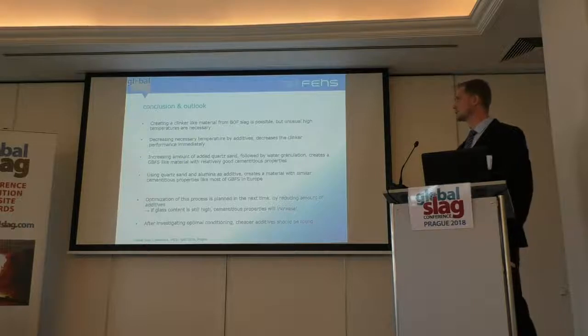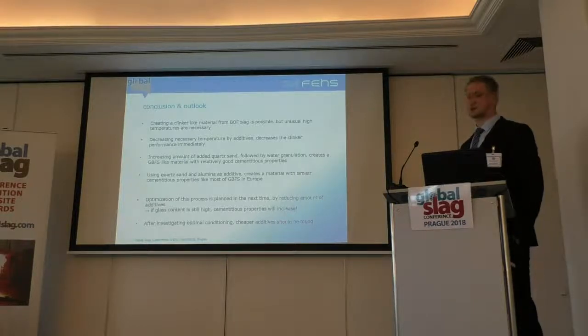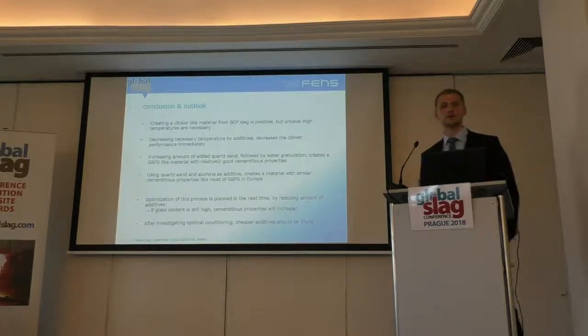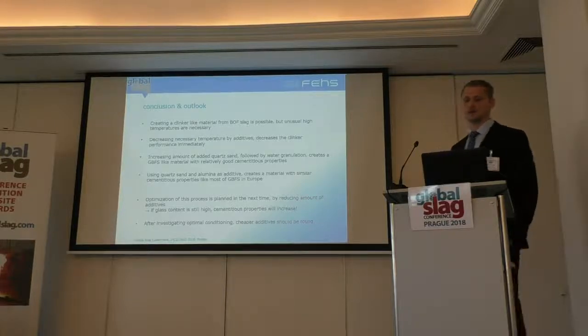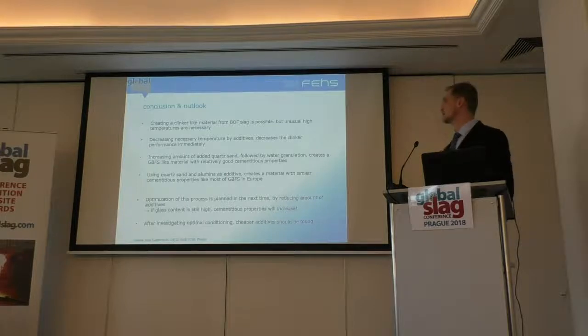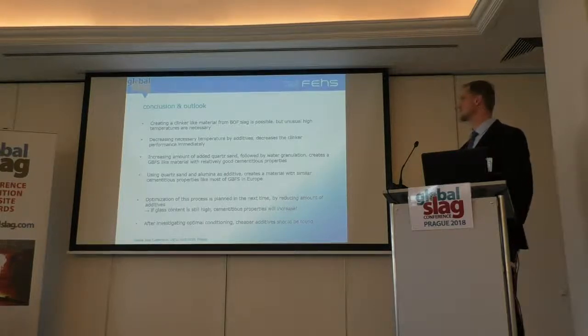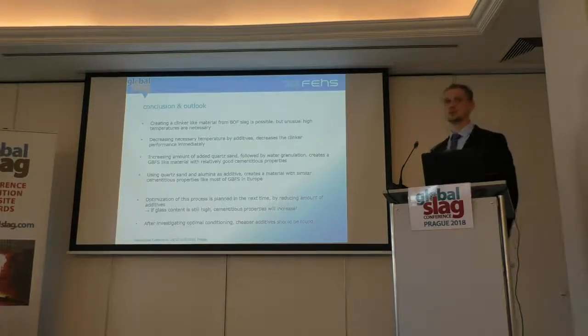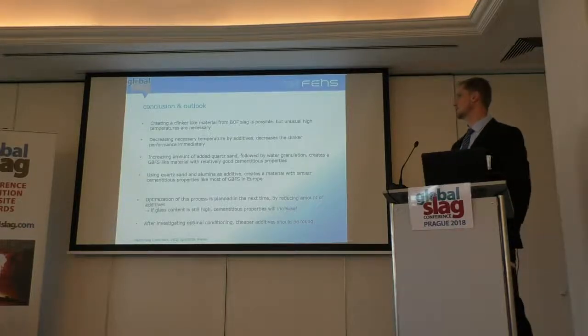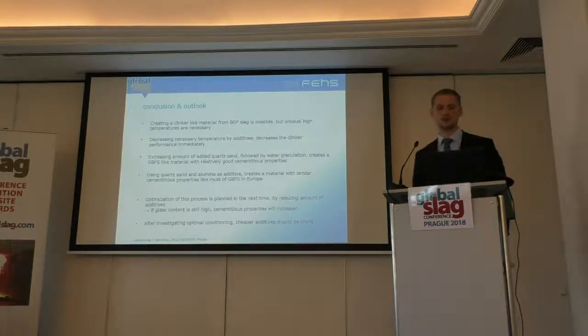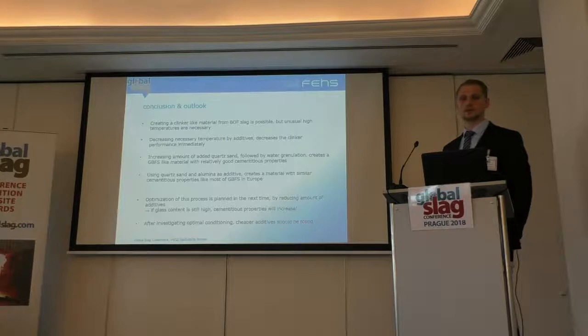So a short conclusion and the outlook. Creating a clinker-like material from BOF slag is possible, but unusually high temperatures are necessary for this. Decreasing the necessary temperature by additives also decreases the clinker performance, and increasing the amount of quartz sand followed by water granulation creates a GBFS-like material with relatively good cementitious properties.